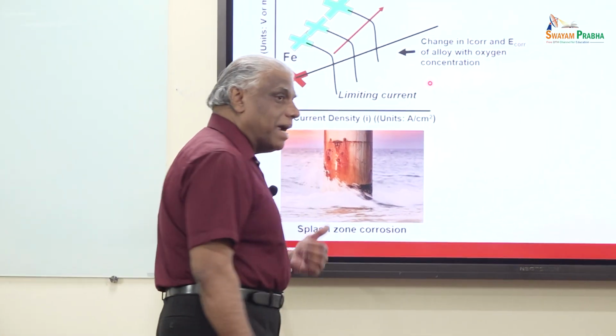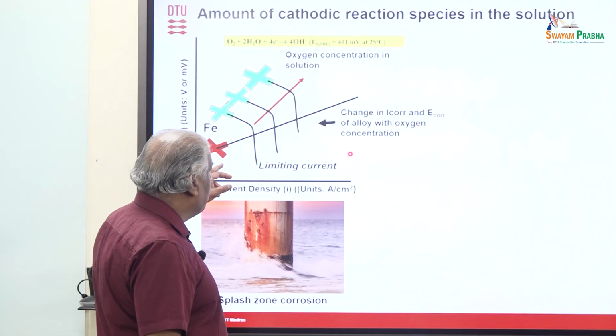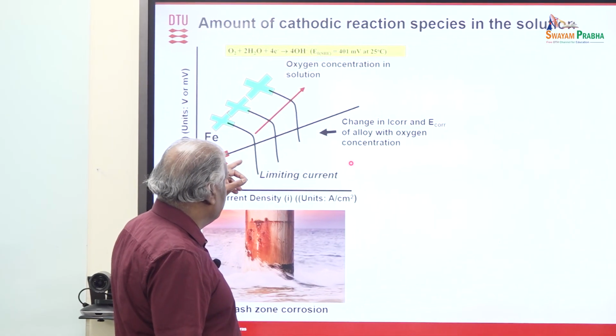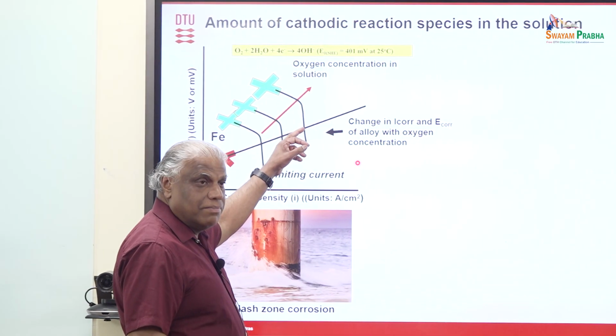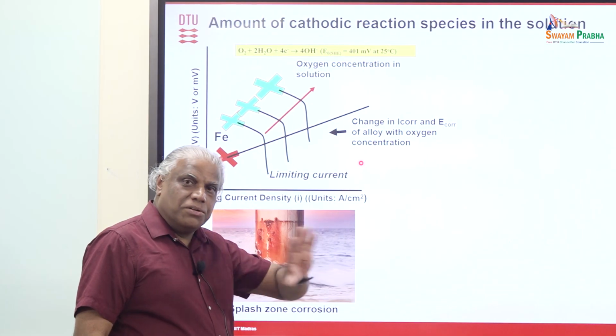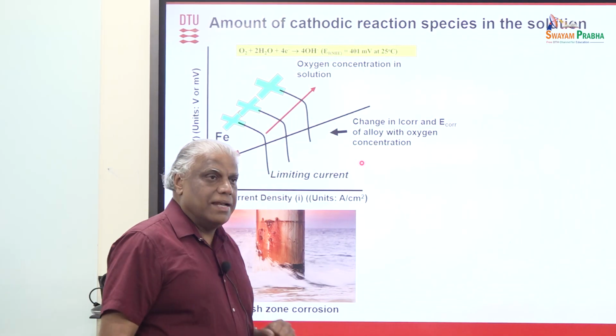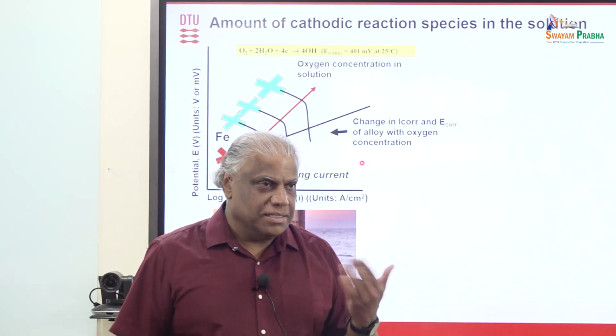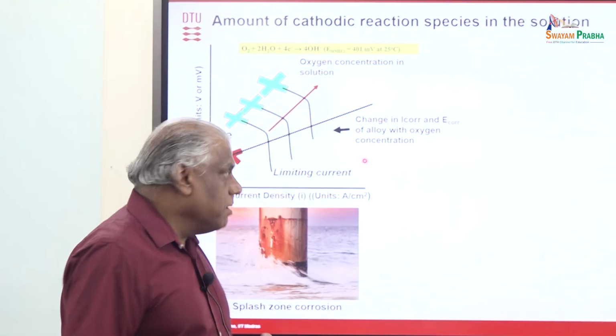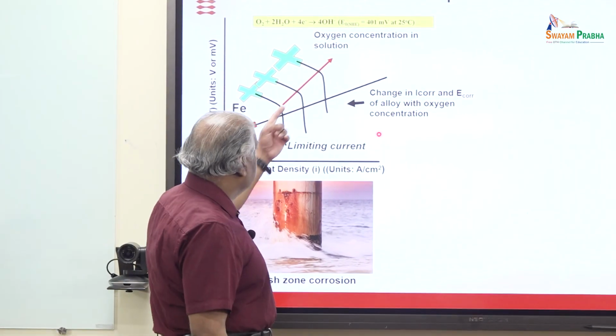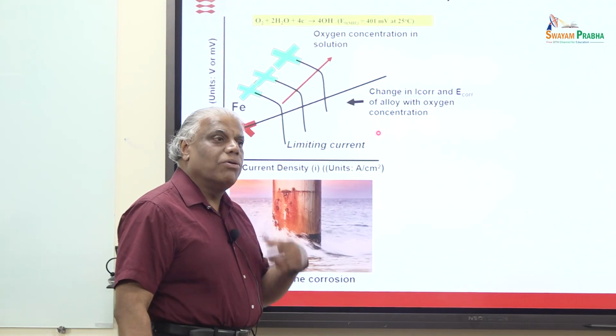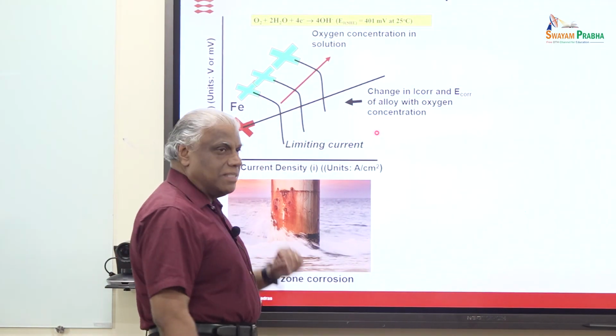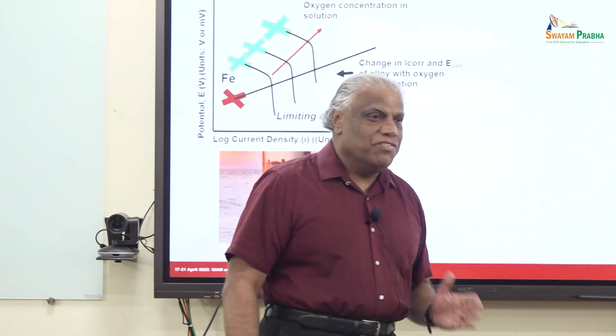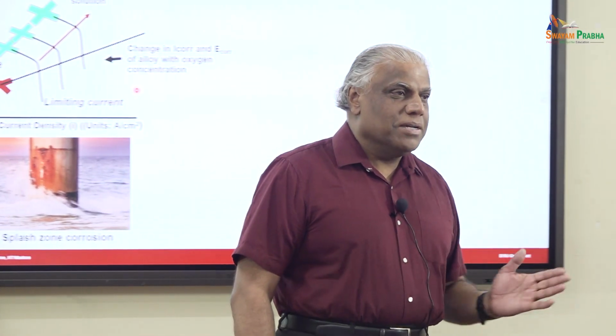What is the good thing and bad thing about the limiting reaction? If you have higher oxygen concentration, more oxygen is there to move to the surface, so you get a higher and higher corrosion rate as oxygen is increasing in the solution. So moving from here to here is with increasing the oxygen concentration. Or you can also think that even with the same oxygen concentration, how can you increase the diffusion? How can you increase the diffusion in a film or a layer or bulk solution?